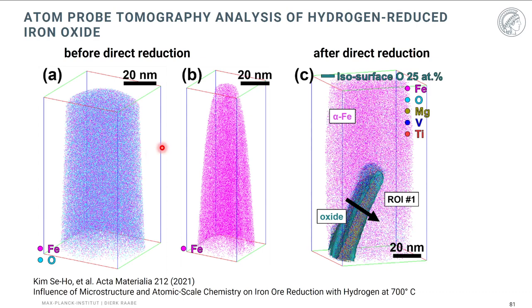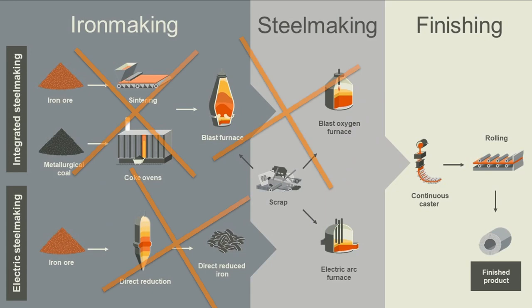We also go to the near atomic scale by using atom probe tomography for these materials. Here you see that before the reduction, you see just the wüstite material. That was a wüstite single crystal. And after reduction, or after partial reduction, you see here the iron, BCC iron that has formed, but you also see, due to the gangue, the chemical tramp material that was in these ores, that some of these oxides have prevailed and remain in the material. And we study their role for the formation of water, for catalysis, but also for the delays in the reduction kinetics.